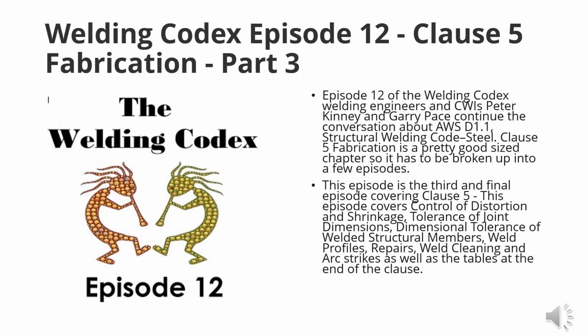Yeah, and then let's see, localized heat repair temperature limitations. Members distorted, this is 525.2. Members distorted by welding shall be straightened by mechanical means or application of a limited amount of localized heat. The temperature of heated areas as measured by approved methods shall not exceed 1100 for quenched and tempered steel, nor 1200 for other steels. The part to be heated for straightening shall be substantially free of stress and other external forces except those stresses resulting from mechanical straightening.